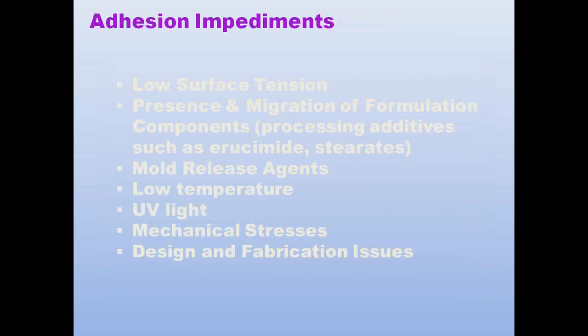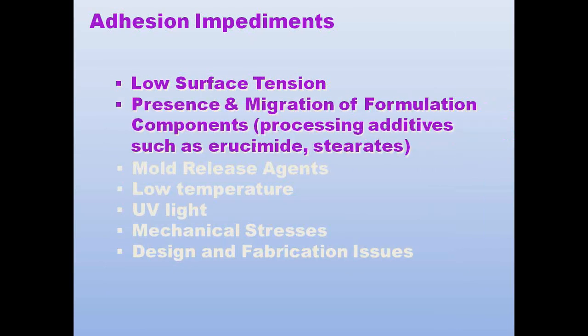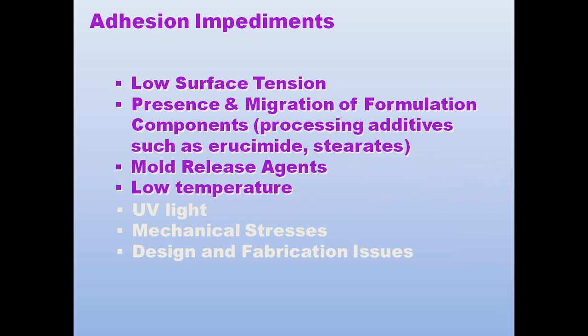Whether it's a composite or whether it's a virgin material, there are some key adhesion impediments that everyone deals with here at Enercon and among our competitors in the industry, and that is low surface tension, also the presence of additives, the migration of additives that are there for processing but get in the way of ensuring that surface energy and the functionality is there for adhesion. Certainly with three-dimensional injection molded pieces, you have mold release interference.